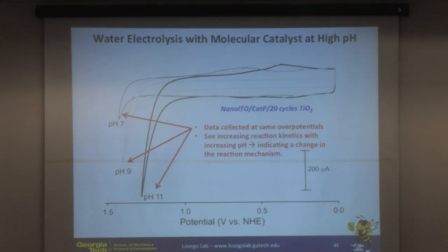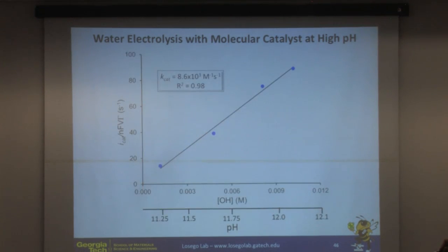And so what we're showing here are the CV curves at the same overpotential. As we change pH, that overpotential is going to shift, so if we go to the same overpotential, we should see the same current. But because we're seeing increasing currents, that indicates we're getting different reaction processes that have faster reaction kinetics. We can verify that at the highest pHs we are getting direct attack from a hydroxyl by looking at the reaction rate, i.e. the electrochemical current, as a function of pH, which is essentially the concentration of the OH ion. We see a linear reaction rate as a function of OH species, which is what we would expect for a first order reaction with a hydroxyl ion.